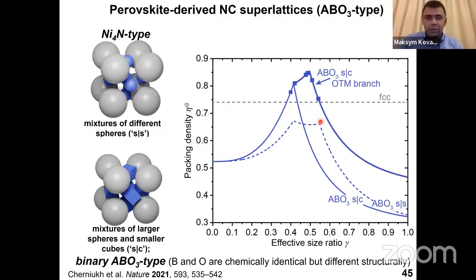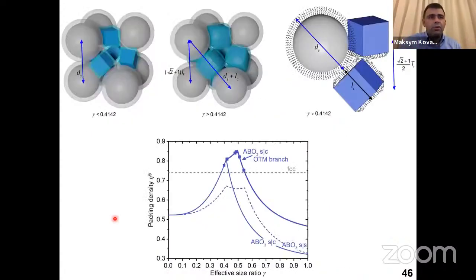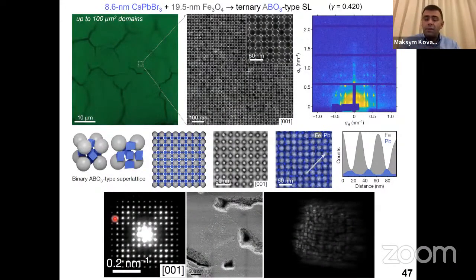And then we checked this range experimentally, and we indeed observed that cubes and spheres do form such a lattice, and this lattice is very much favored compared to the phase separation. So you end up with a very nice, very clean yield of this structure. It outcompetes phase separation by far.